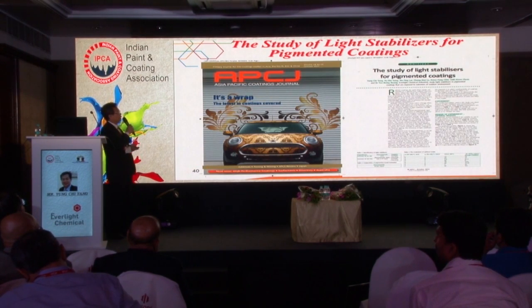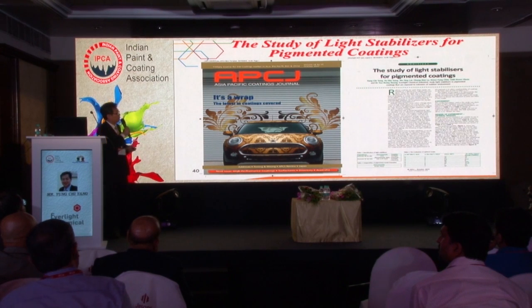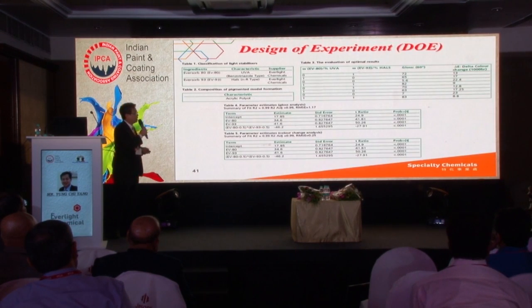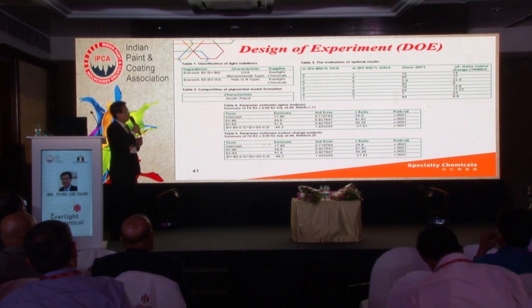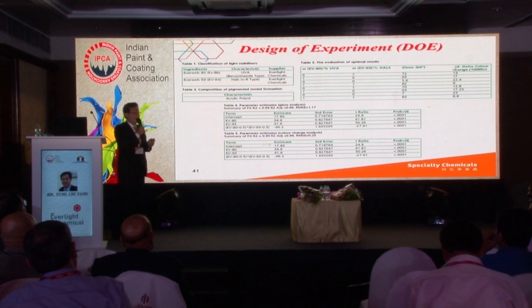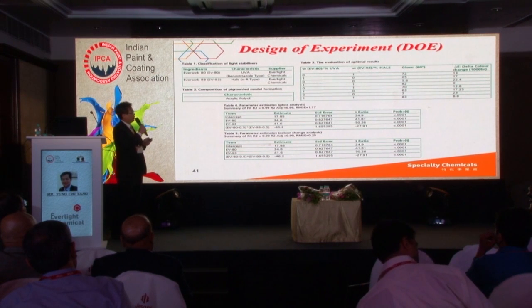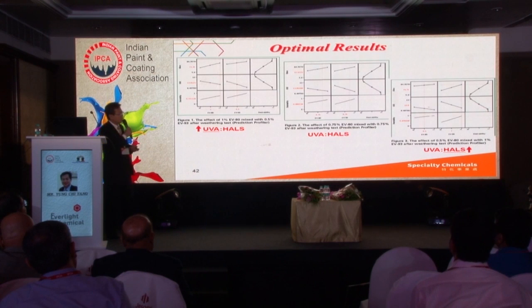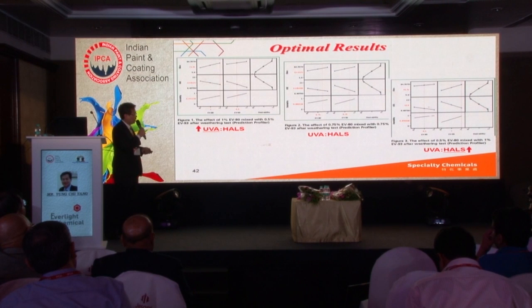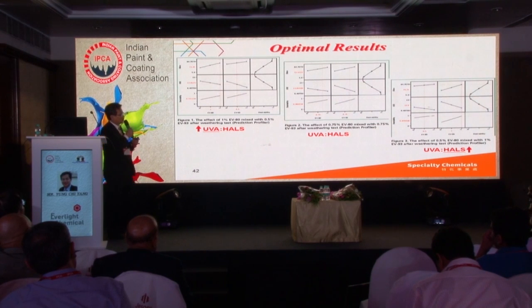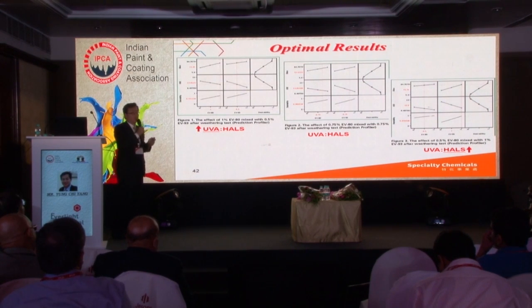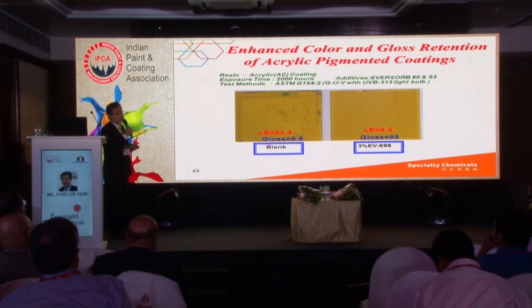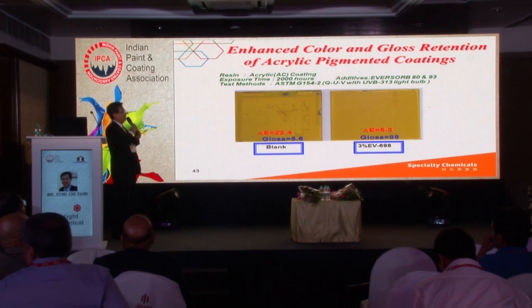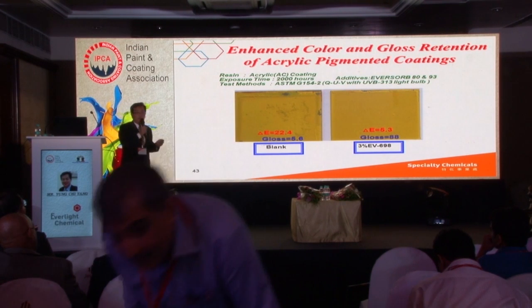So we have a study of the pigment system. In this case, I just show you two levels, two factors: the UV absorber and HALS, and two levels, 0% and 1%. From this, very interesting, you can see the high ratio of UV absorber and the high ratio of HALS. So which of the two is good performance for the pigment system? According to our test, with a high ratio of HALS, you can get the best performance.